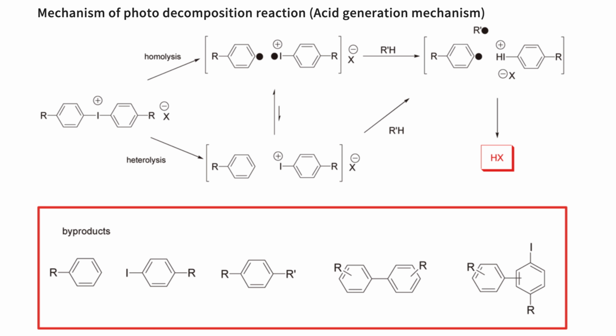In the case of iodonium salts, UV irradiation induces both homolytic and heterolytic cleavages of Ar-I bonds to yield highly reactive cations, radical cations, and radicals. However, these are not the primary initiators of cationic polymerization. The initially formed cations and cation radicals react further with proton-donating species such as water or alcohols present in the reaction mixture to form Brønsted acids that are the primary initiating species.